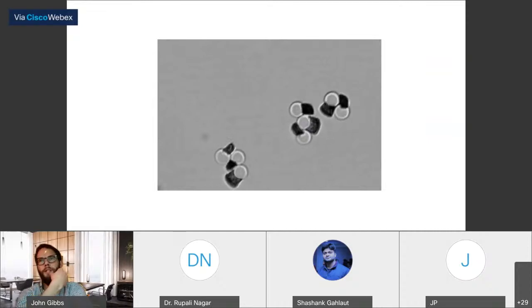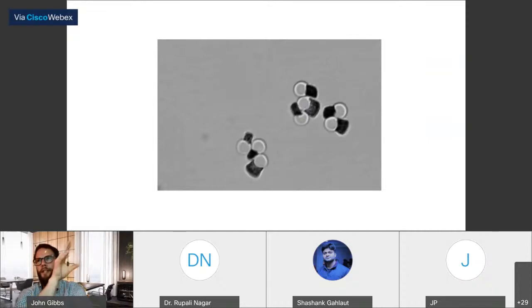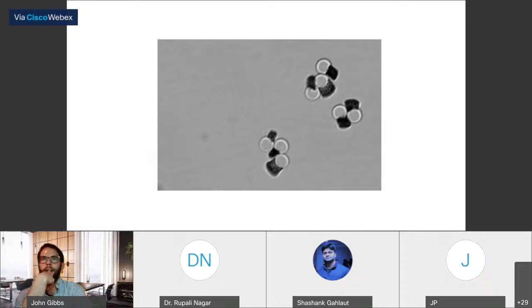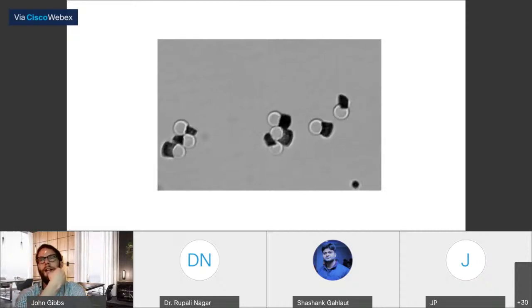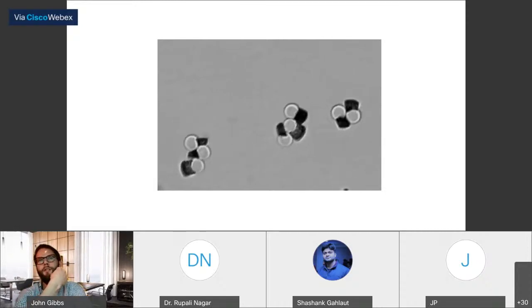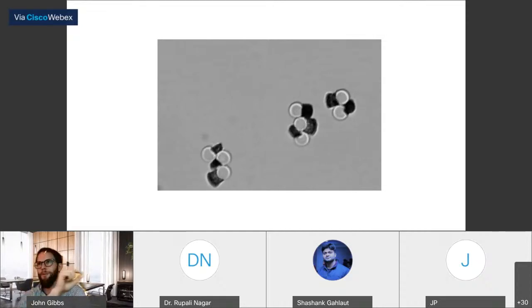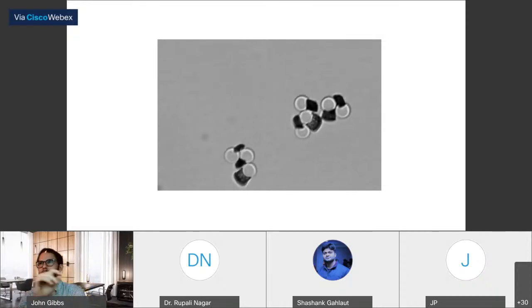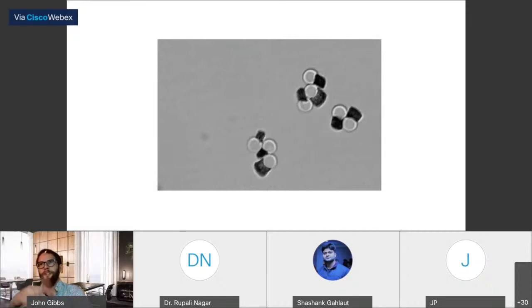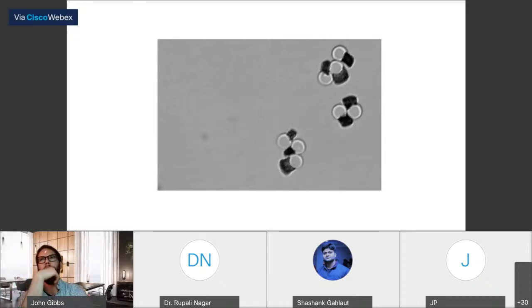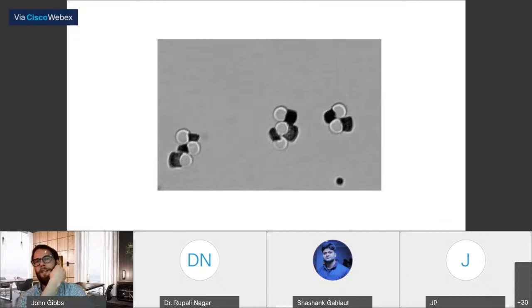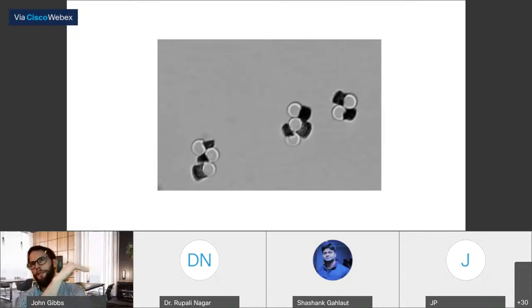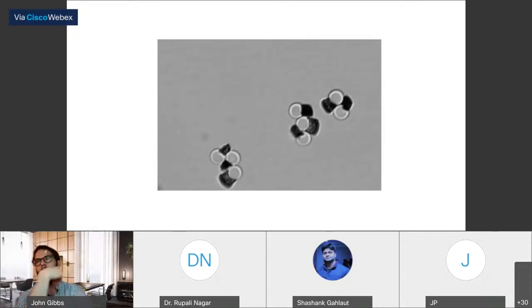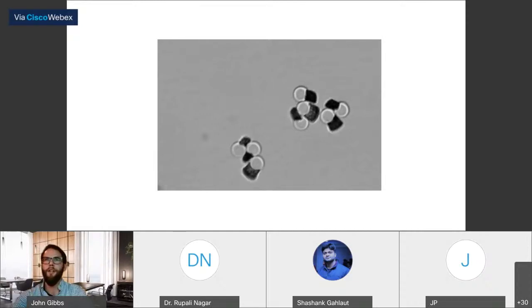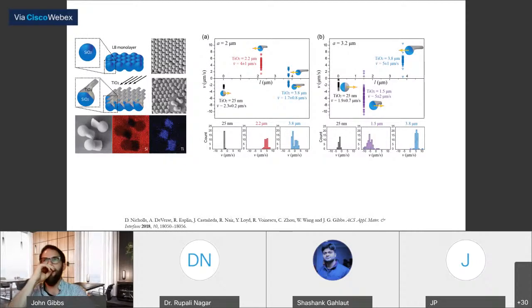But one thing you might notice with these is that you can really see the structure. And I think that everybody who messes with GLAD is probably aware of the fact that you don't get perfect repetition of the structure across the entire substrate. You get these small variations and so forth. You can see that in some of these particles. You also see that they can orient themselves differently, but there can be a little bit of variation. And that's what we expect to be the cause of the spreads and the different velocities that we're measuring here.